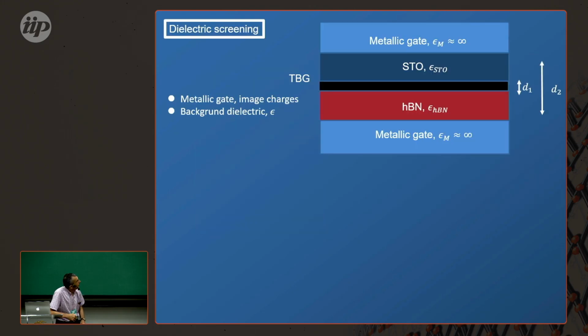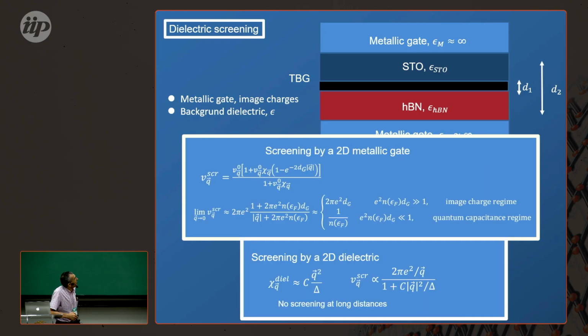That, by the way, leads to an interesting question, because the environment is a very convenient knob for experimentalists. They can tune the environment, and we theorists have described the environment as built up from metallic gates, which are described by image charges, and a background dielectric. And none of the two approximations are too reliable.